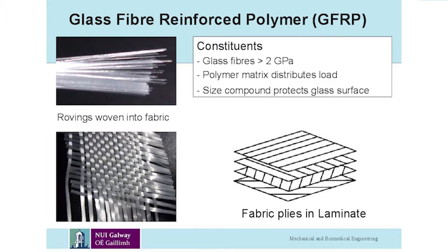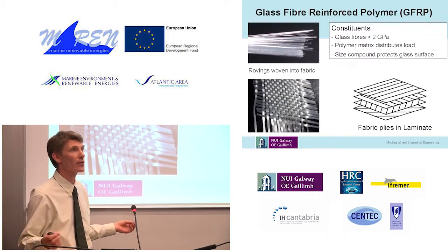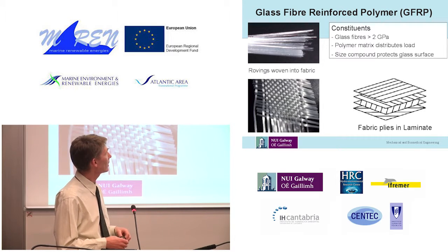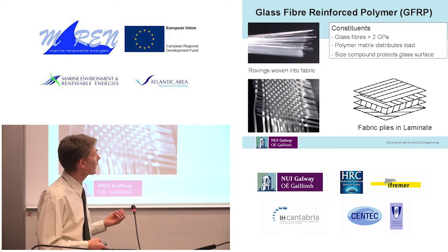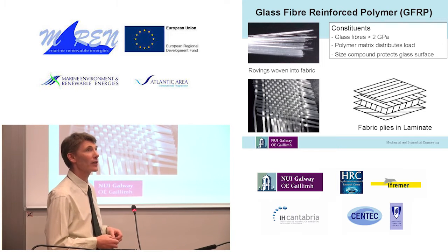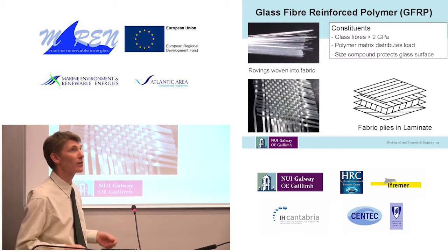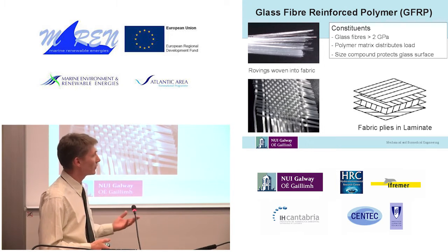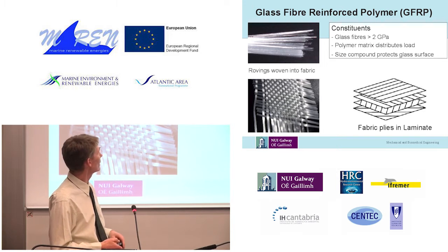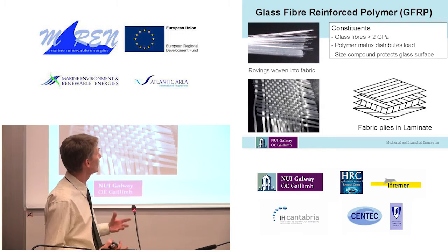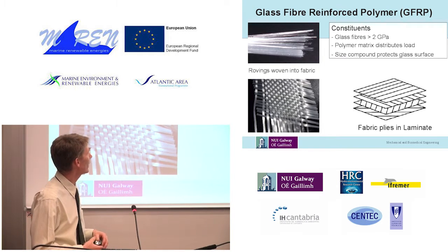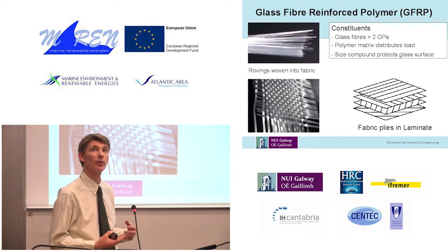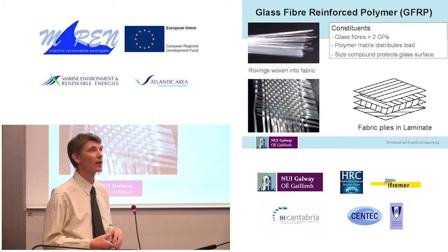Okay, so just a quick overview of the material itself. The glass fibres used in fiberglass are actually very small in diameter, and by stretching them out to these very tiny dimensions, essentially what happens is that the flaws that are in bulk glass get distributed very far apart, and they're no longer important for the strength of the material. So then there's a polymer matrix that's injected around the glass fibres, and that helps to distribute the load among all the glass fibres, and it kind of turns it into a solid material.